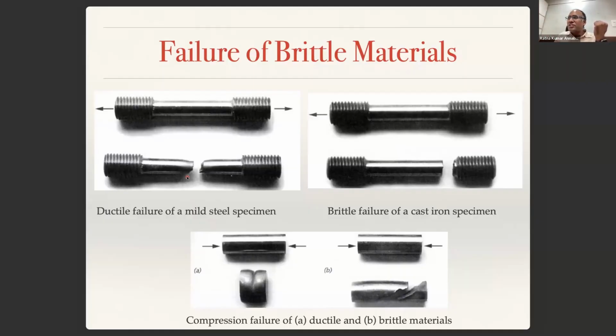Why would the plastic deformation take place on a plane along 45 degree angle? Because of shear stress, because shear stress is maximum on that plane. The plane which is oriented at an angle of 45 degrees to the loading axis is the plane in which you will have maximum shear stress. So, since this plane is subjected to maximum shear stress, it is very likely that the same plane is going to break when it goes beyond the ultimate strength. That is why you have a 45 degree plane.